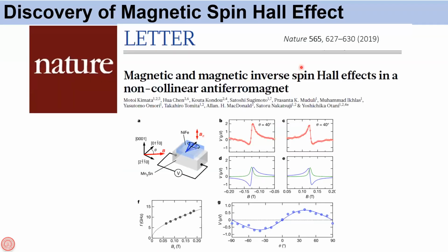Here I will show you some of the previous work that actually motivated us to work in this area. It was the discovery of the so-called magnetic spin Hall effect in 2019, where they were performing inverse spin Hall effect measurements on bulk Mn3Sn, and they saw a symmetric component that doesn't change sign as you reverse the direction of the field, and this was attributed to the magnetic spin Hall effect.